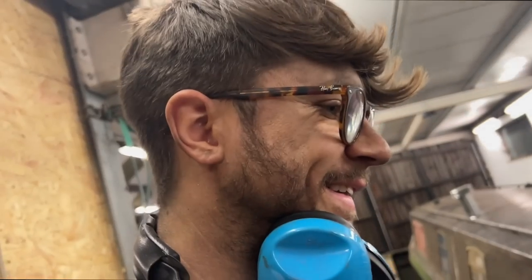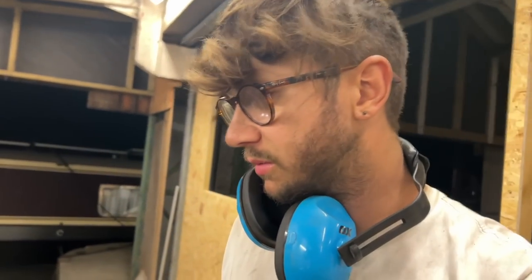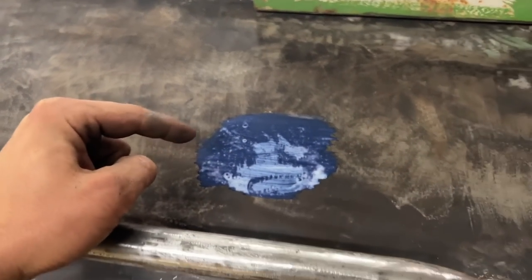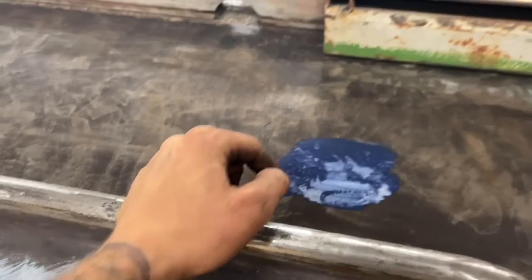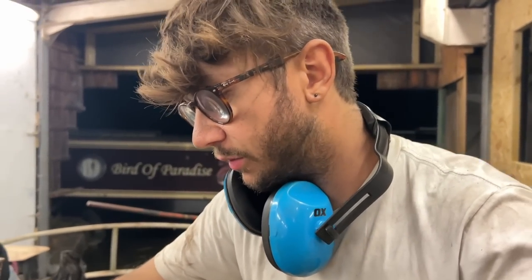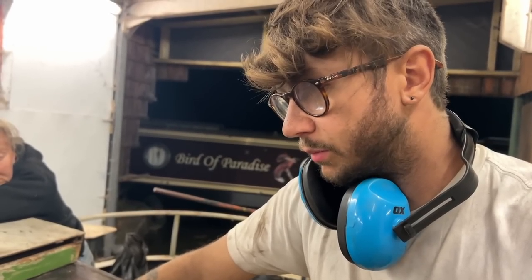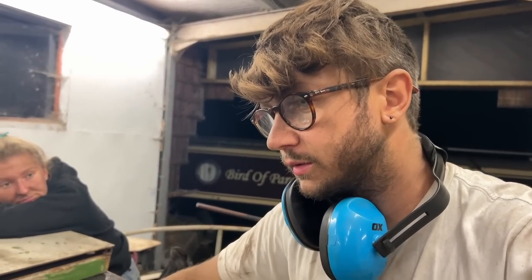So carrying on from my experiment, I've been doing a bit of research, and this is black rust, which I didn't even know was a thing, but it's basically a thin film that forms in low oxygen settings, so essentially under a layer of paint. It's fairly stable, but obviously once you sand it, it goes orange, and then you can wipe it away, but it's quite hard to get rid of. I'm just trying some Vactan on it as well, and it's not reacting to the Vactan per se. It's also not leaching through our zinc primer, so I'm fairly confident you might be able to just zinc primer it, which is a rust inhibitor anyway. Problem is, it's just a lot of paint to scrape back off if it doesn't work.